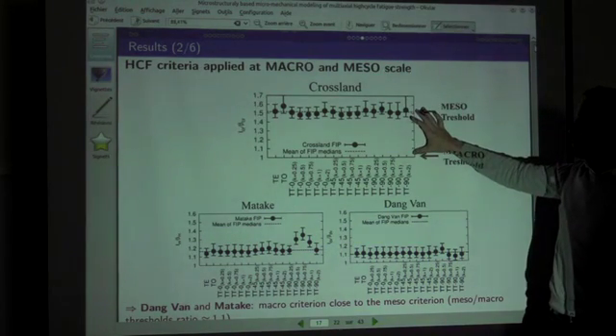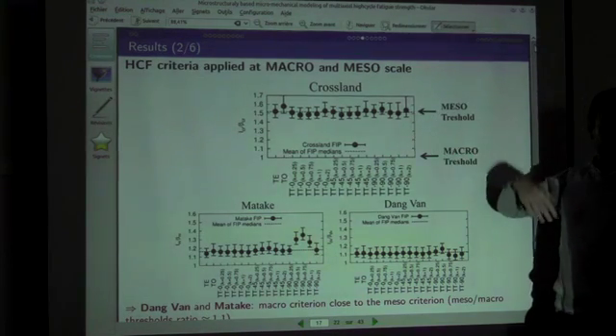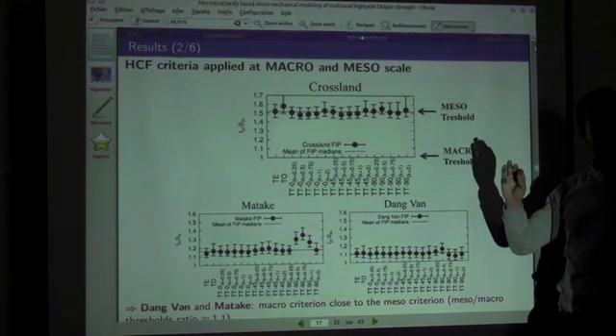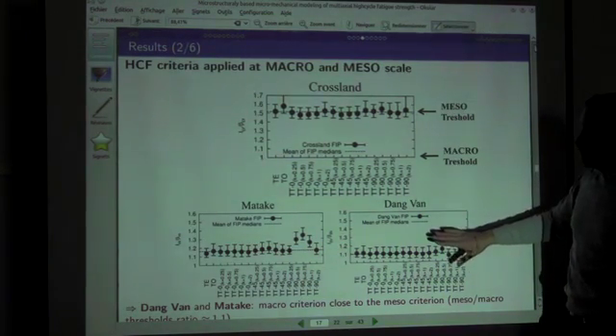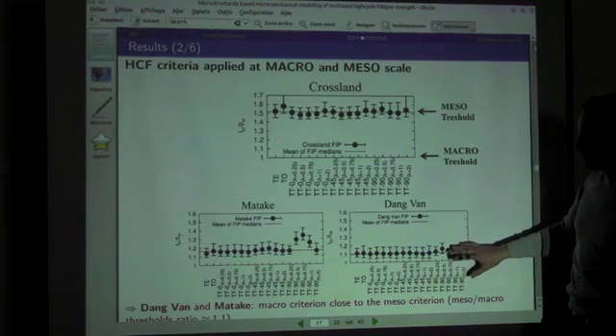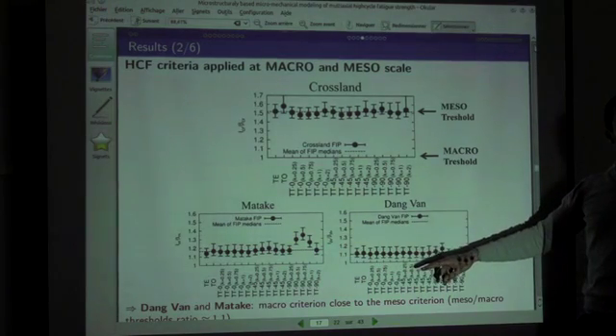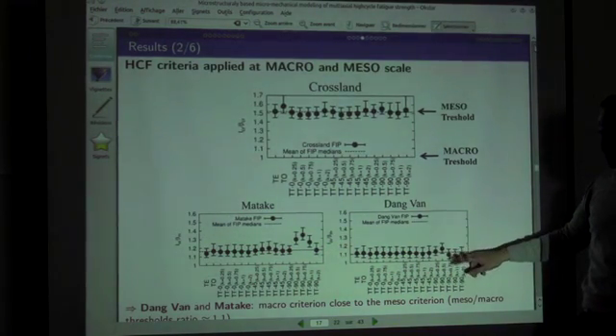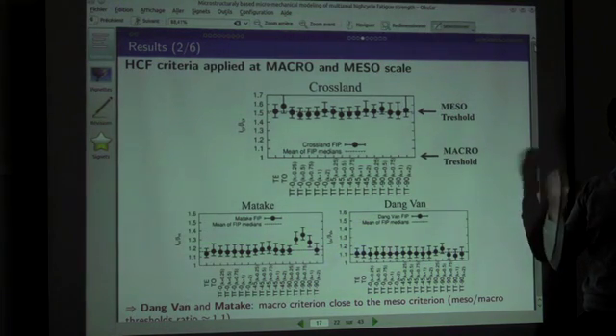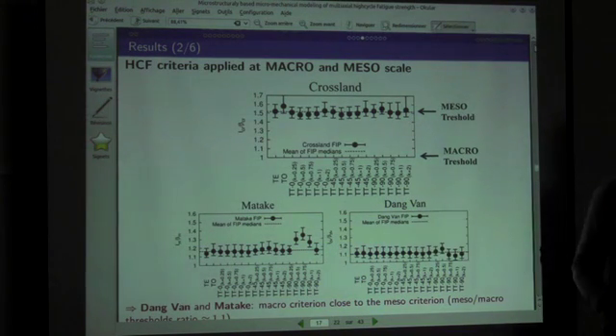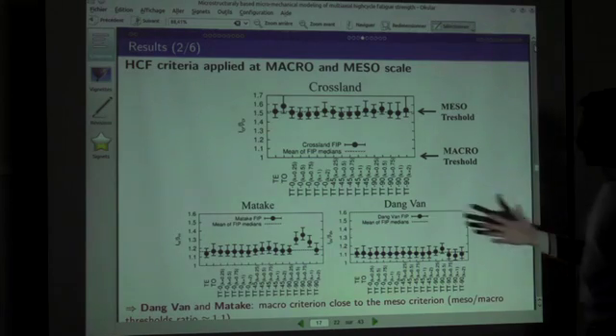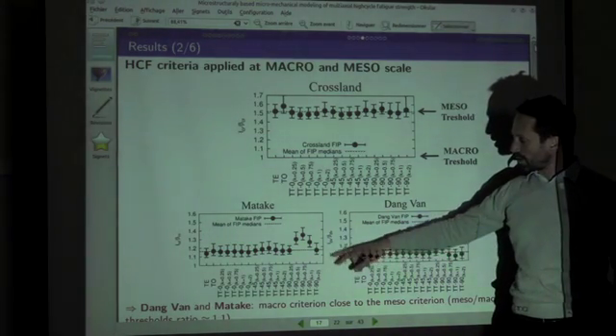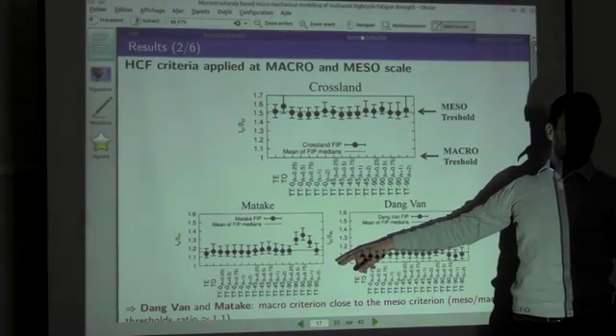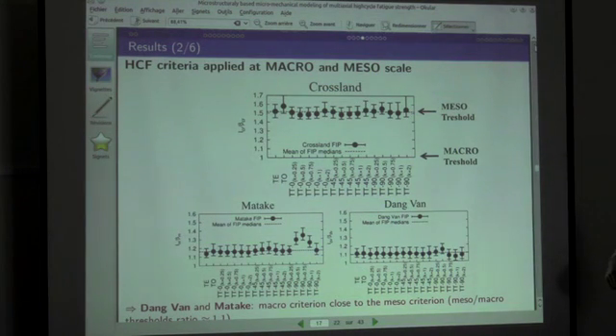And the higher this parameter, the closer the meso criteria is to the macro criteria. For example, here you see that if you use some shear stress-based and normal stress or hydrostatic stress-based criteria, but shear one, maximum shear plane, a critical plane approach, you will be much closer to the macro response. So it means that those parameters give a good evaluation of the response at the micro scale, which is mostly based on the fact that you are at the maximum shear critical plane based approach, but also here this difference is due to the fact that you use elastic anisotropy. You have elastic anisotropy introduced and you modify the stress and strain parameter that you include in your computation.